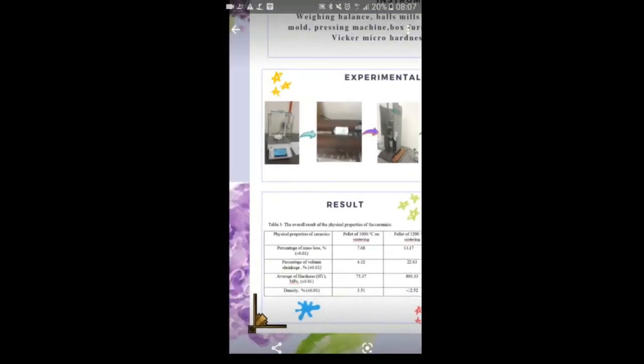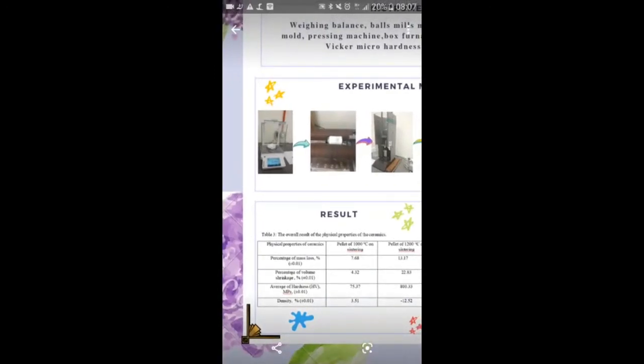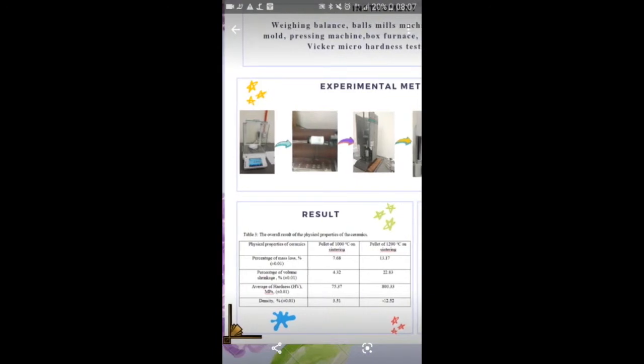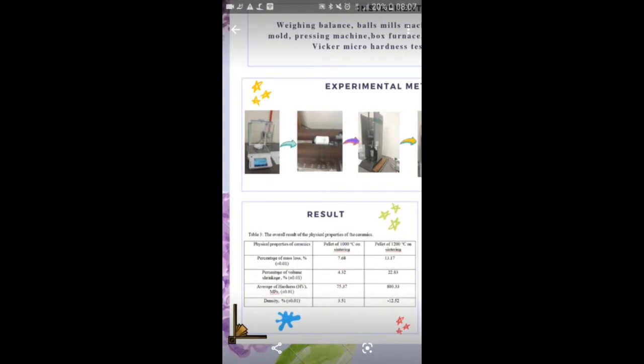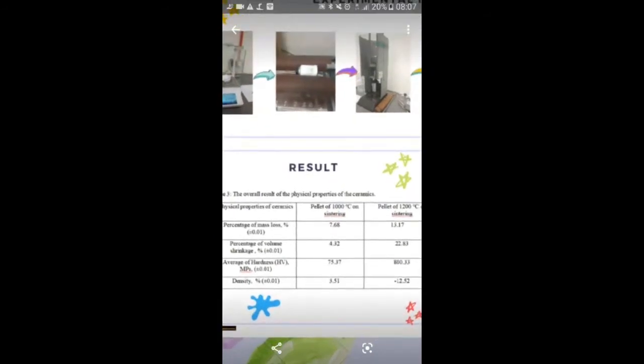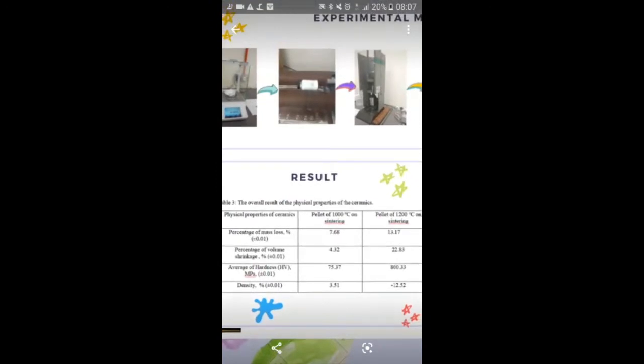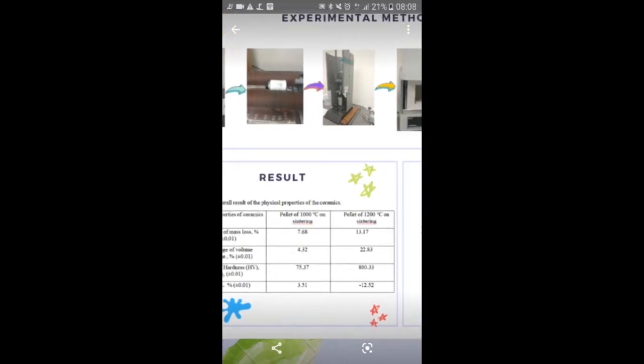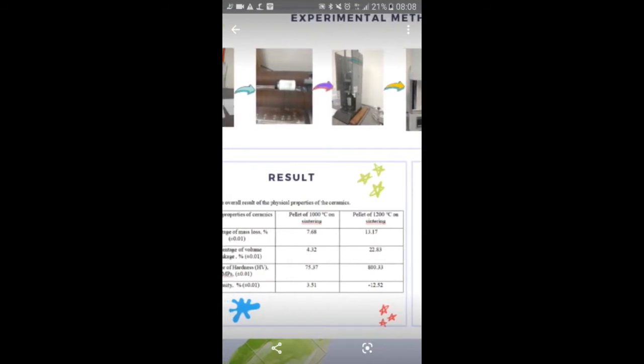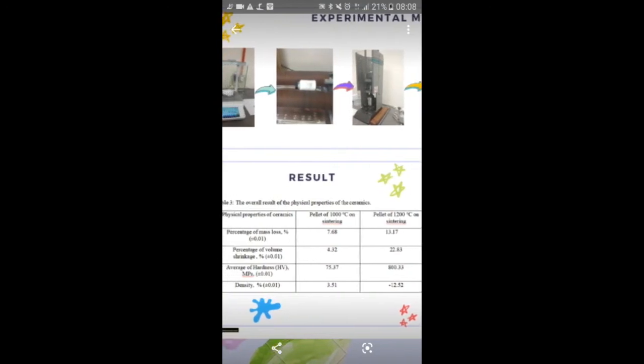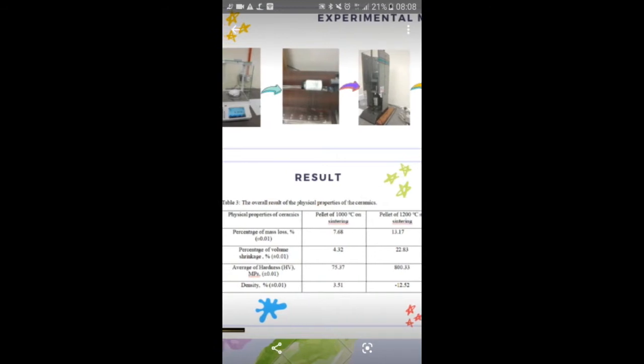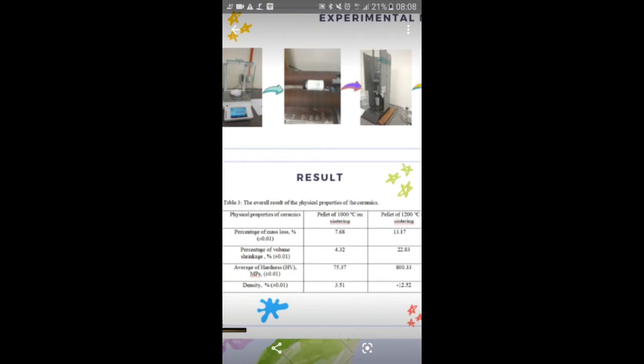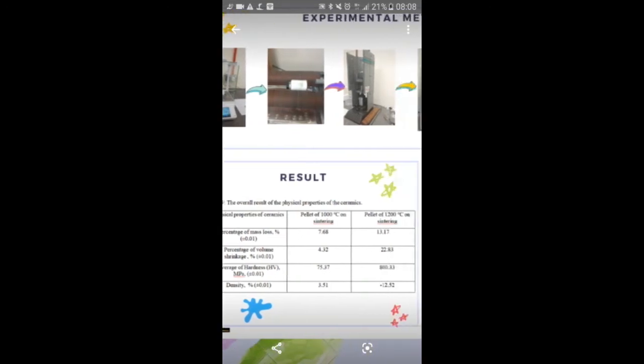The volume of pores and the pore surface area may affect the hardness of the ceramic. The material hardness was determined by measuring the size of the indentations made by a sharp diamond pressed strongly on the ceramic specimen. In this experiment, the hardness reading increased from 75.37 to 800.33 megapascal for 1000 degrees Celsius and 1200 degrees Celsius respectively. So the ceramic sintered at 1200 degrees Celsius was harder and has a higher density compared to the ceramic sintered at 1000 degrees Celsius.